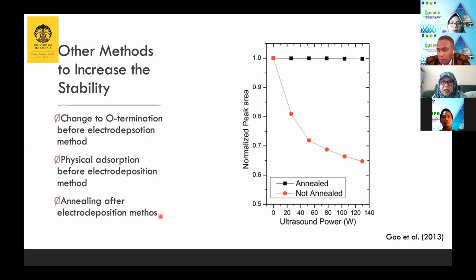We can also do annealing after the deposition methods. So we put it under very high temperature. It will give some energy, and the rearrangement of the metals or the particles will occur, and then we can get better stability. So this is the test using ultrasonication. This is without annealing. Some particles will be removed after some ultrasonication, but with annealing, stability is much better than this.